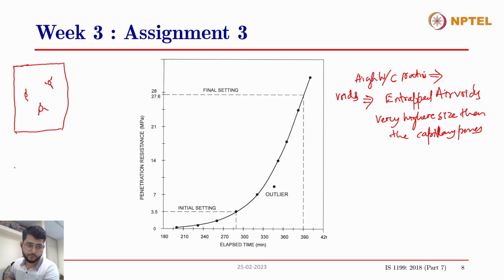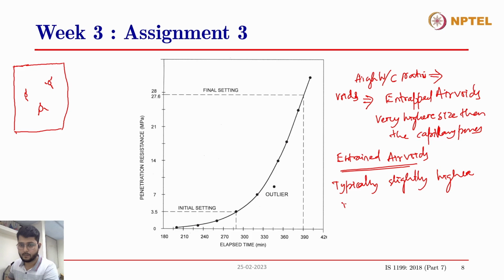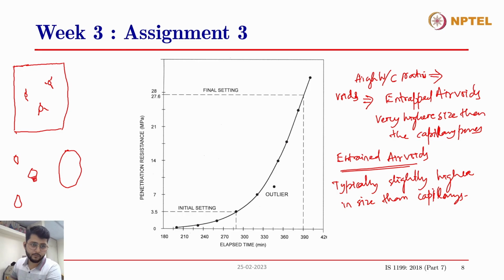But this can be reduced by entrainment of air voids, which are known as entrained air voids, using air entraining admixtures. These are typically slightly higher in size than the capillary pores. So what happens in the case of entrained air voids is that when these capillary pores are present inside the concrete, and there is another entrained air void over here, the water in the partially filled capillary pores, instead of freezing in these pores, gets sucked out into the entrained air voids, which have a larger volume and hence a larger space for the water to freeze.